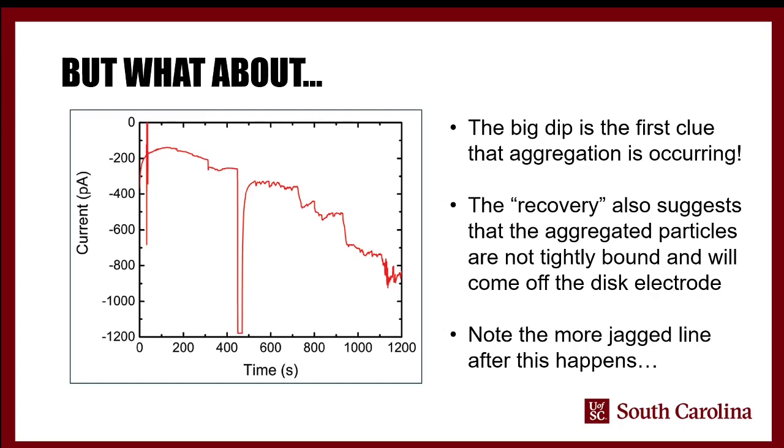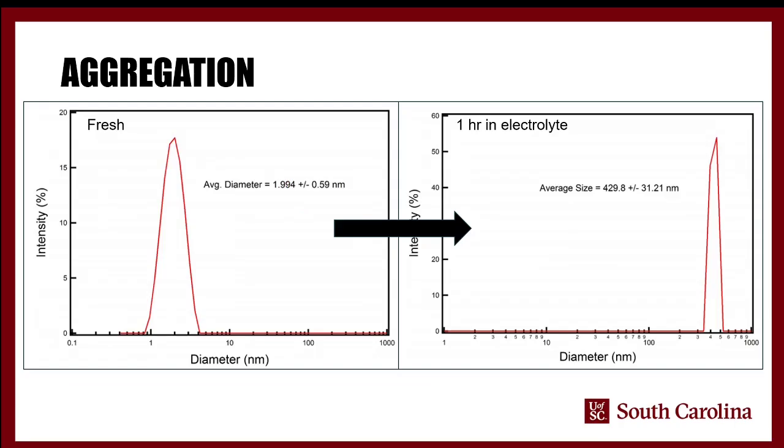And what's interesting about that is it changes the frequency of the collisions. We predicted a very low collision frequency of about 0.07 per second, and what we actually got was up to about 0.7 per second with this aggregation happening, which resulted in a mass of particles near the electrode that effectively provided almost an artificial increase in the rate of collisions.